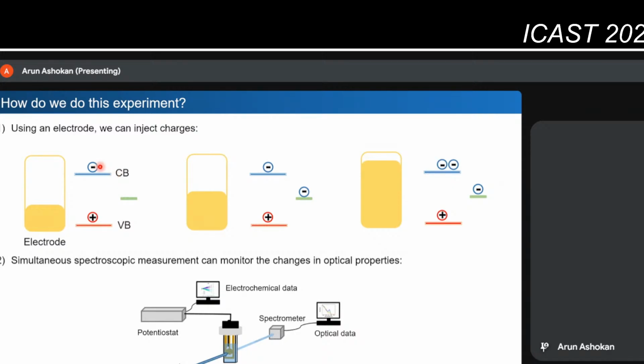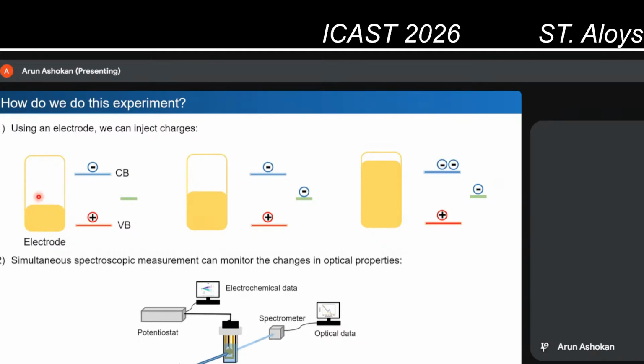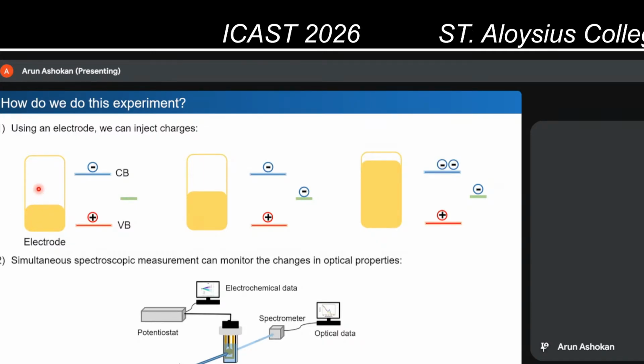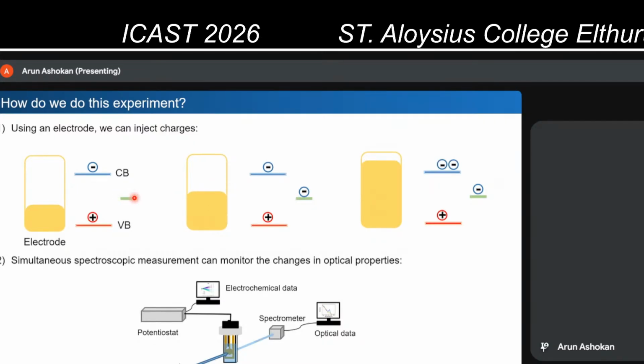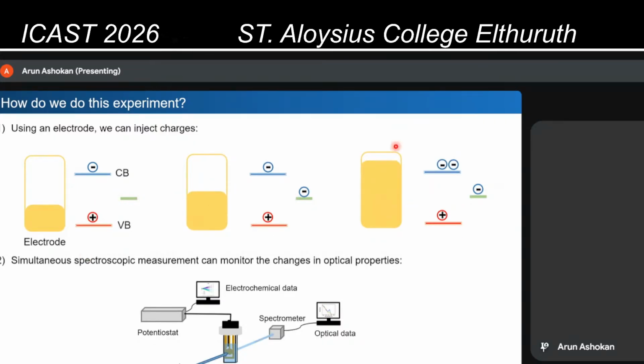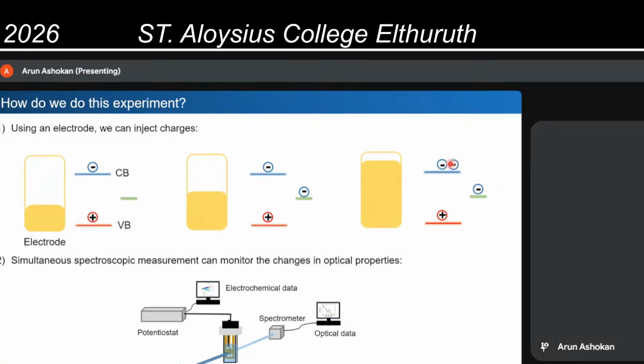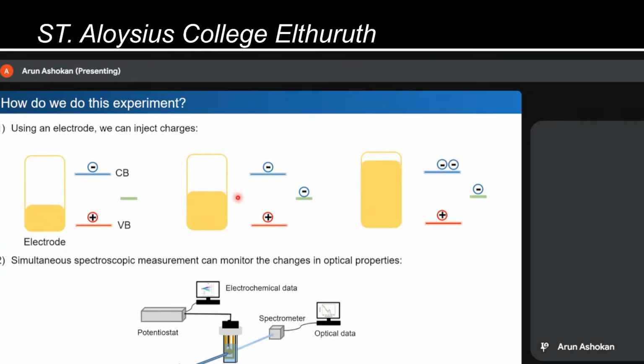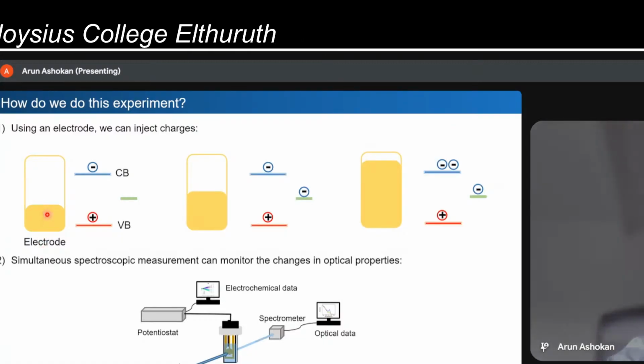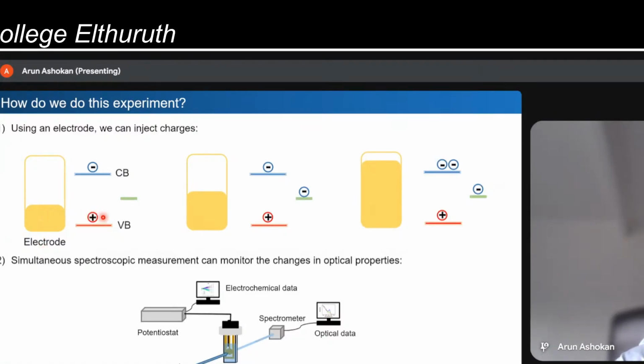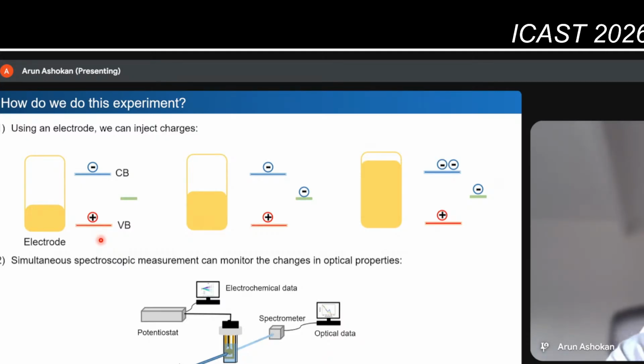So I'm charging a semiconductor, so it has a valence band and a conduction band, and you're shining light, so you'll definitely form the exciton. You have an electrode. When you raise the Fermi level of this electrode or apply potential, you slowly start filling the trap states, and even further, you can start filling the conduction band. This process can go the other way. If I reduce the Fermi level or go to oxidizing potential, we can fill a lot of holes here, and you can do the charging. And simultaneously, we will do the spectroscopic measurement.